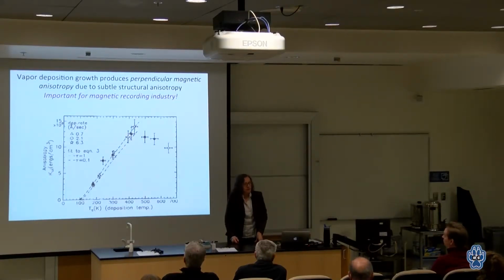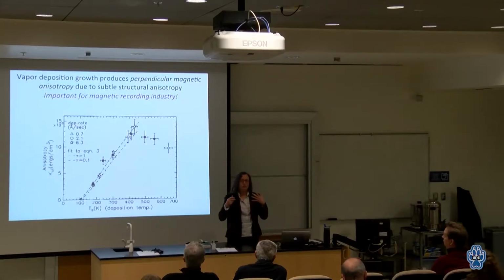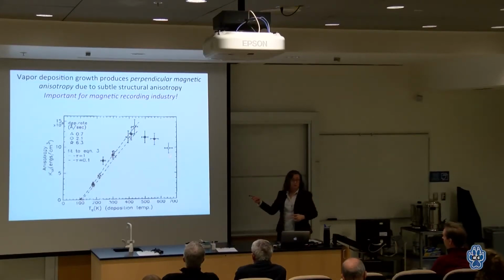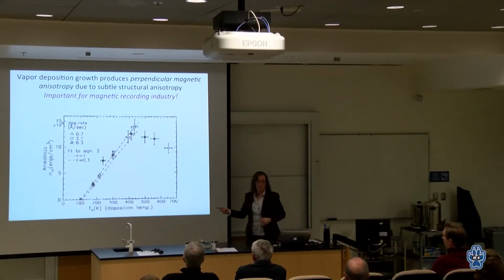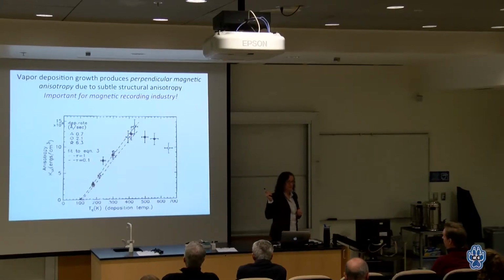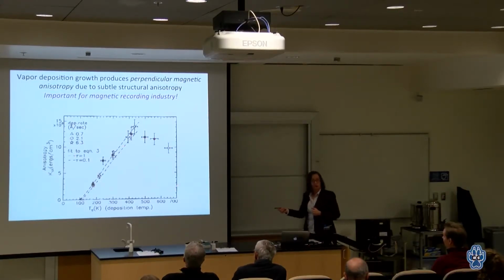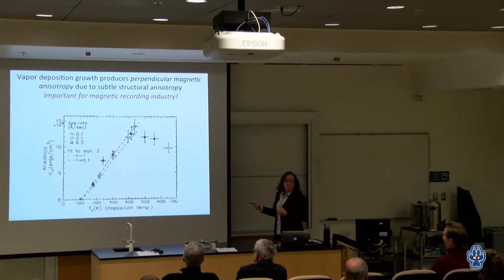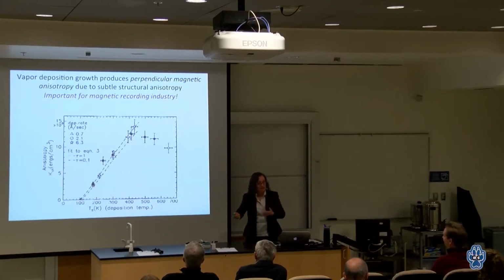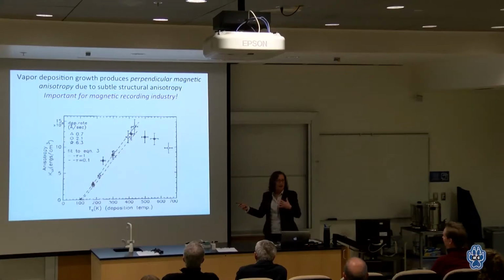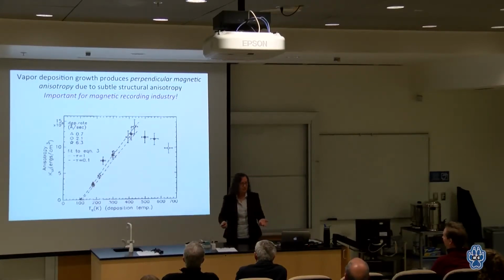So what do I mean by that? Well, the first thing is you would think that amorphous would mean that all directions look the same. And in fact, this plot is literally a scan from way back before we had computers to make graphics. This is from my postdoc period. So I was actually giving an interview talk for an assistant professor, and I talked about it, how this is anisotropic, and one of the audience members actually said, if it's anisotropic, it can't be amorphous, because amorphous, by definition, should be the same in all directions.